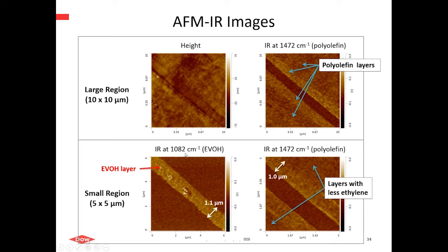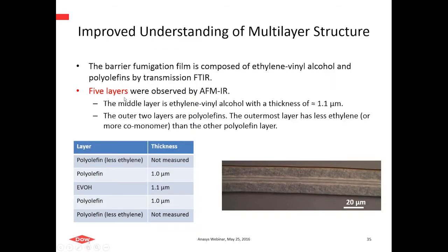When we map the CO stretch associated with the EVOH, we see that lights up nicely in the central layer and gives us a much better definition of that layer as well as its dimensions. We can see that quite clearly. So we can put together a better story of what the composition and structure of this barrier film is. It really is now a 5-layer structure, essentially an ABCBA, with EVOH in the core with a better definition of that core dimension. And then the 2 outer layers are polyolefins with varying ethylene content, probably different comonomer content in the 2 adjacent layers relative to the outer 2 layers.